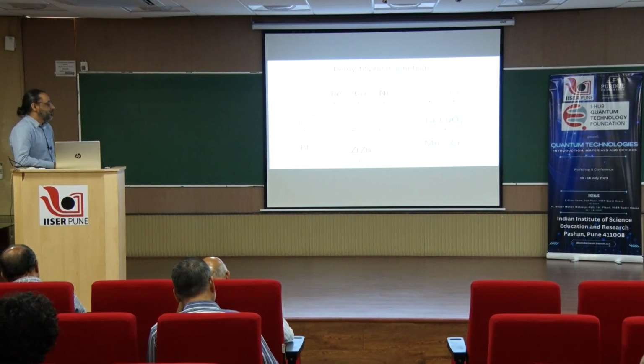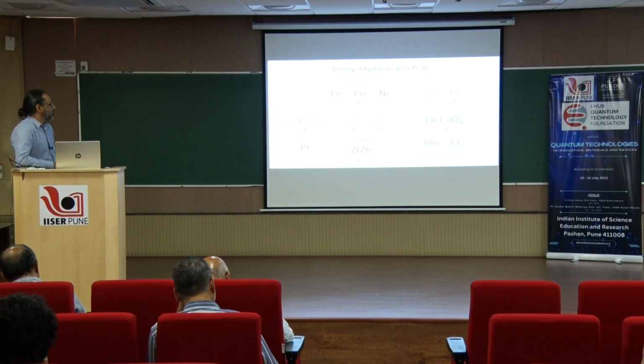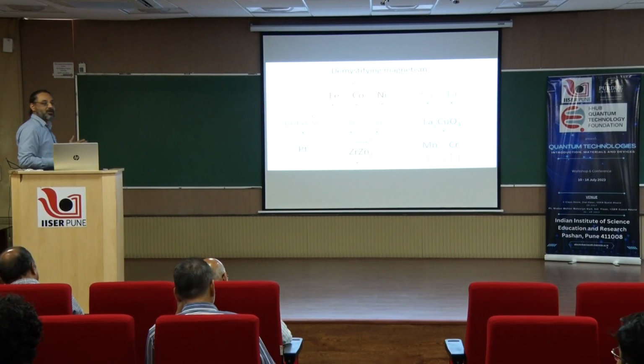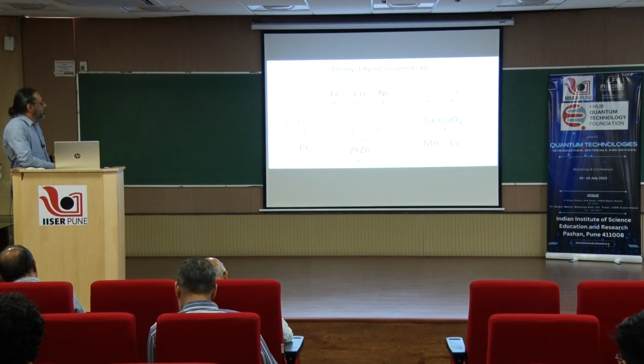Okay, so you get a new material out of these two non-magnetic materials to start with, and this guy happens to be a ferromagnet. All right, and this ferromagnet is not the same as the ferromagnets that I have listed at the top, because the ferromagnets listed at the top can be explained by quote unquote classical theory or the Stoner criterion, but this is a special ferromagnet which is called itinerant weak ferromagnetism. So, that emerges out of two apparently non-magnetic material.